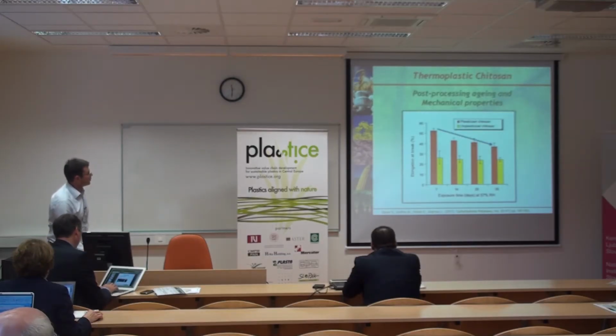And more or less, very similarly to starch, you have to wait about 1 month to reach stable properties. Here you see a fast evolution important during the 1 or 2 first weeks, and then it's much more slow, and you reach almost constant properties after 1 month of storage. And plasticized starch shows higher differences in evolution due to higher content in water in the material.